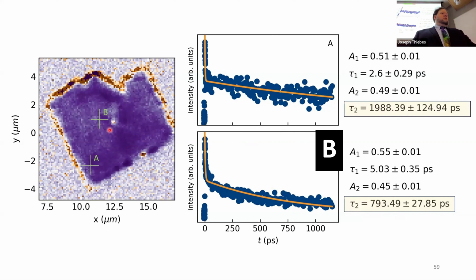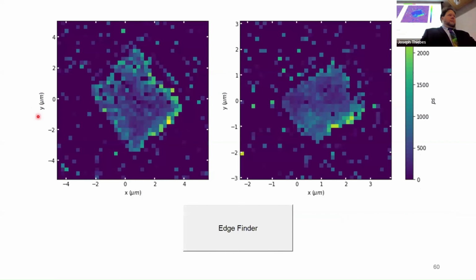So in order to avoid the possibility that I was just getting lucky, we started doing excited state lifetime imaging, which is where we basically took a lifetime measurement at every pixel on the crystal and then mapped them. And this is the first result here. These are crystals, and these are lifetimes that we measured at each place. And this is of the 2 lifetimes we fitted. This is the second one, the longer of the 2. And it's visually obvious here. It's yellower along the edges, and that was encouraging. But being, I want to say persnickety, but as picky as I am about making sure that the noise isn't confusing us, I wanted to make sure.